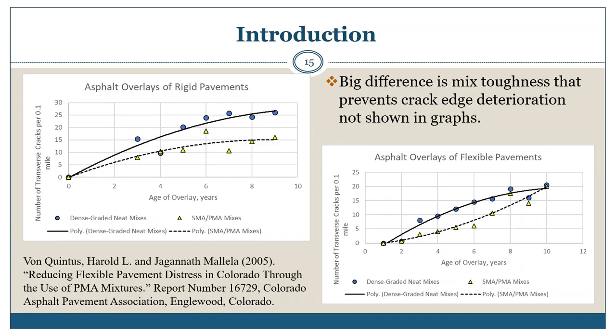Continuing with a comparison of SMA and conventional dense graded mixes, this slide illustrates a graphical summary of data collected by the Colorado Department of Transportation showing the cracking in the asphalt overlays of rigid and flexible pavements of SMA mixes versus conventional dense graded mixes. With the graph on the left, the dense graded neat asphalt mixes exhibited much more transverse cracks on a 1/10 of a mile basis as compared to the SMA and or polymer modified mixes over time.